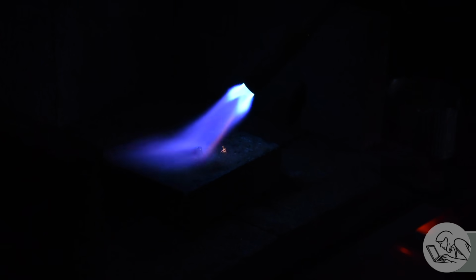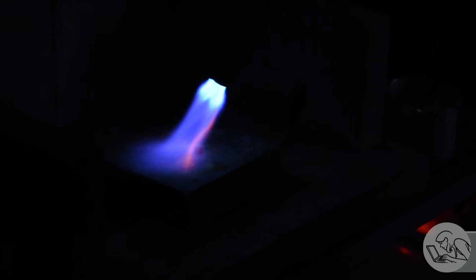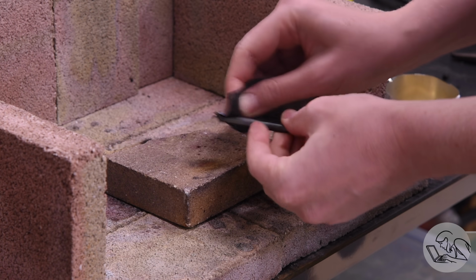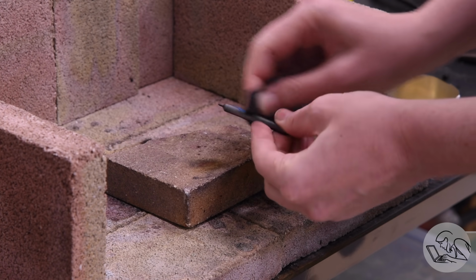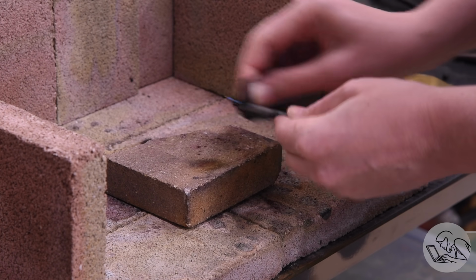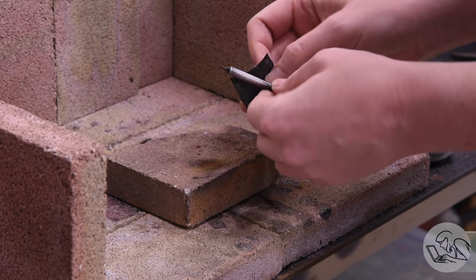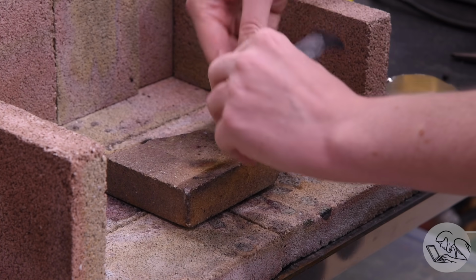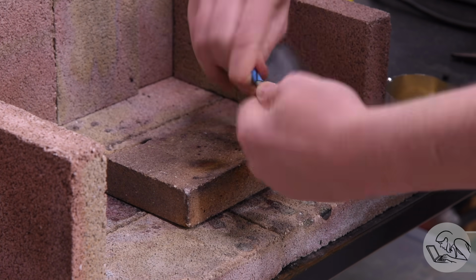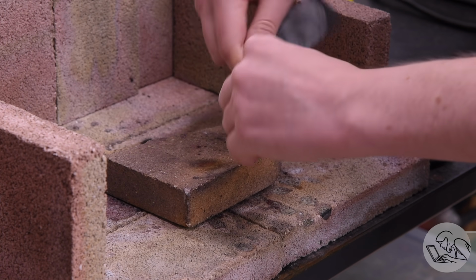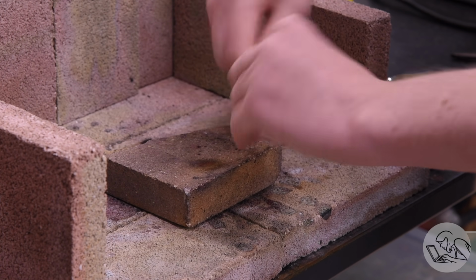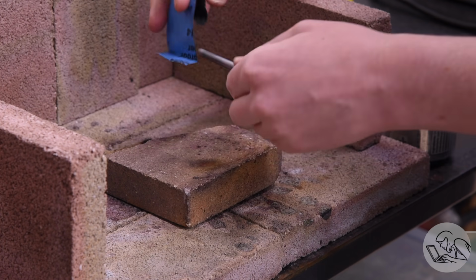This step is pretty foolproof. As long as you've seen that steel glowing orangish red for a couple of seconds and you quench it immediately in the right liquid, it'll harden. And this is the hardening step. It's now very hard. Too hard, in fact. At this point, the steel will be brittle, so we need to temper it and give it a little bit of flexibility. For this, the material has to be clean and have a good surface finish so that we can see the color of the steel. That's very important on this step.